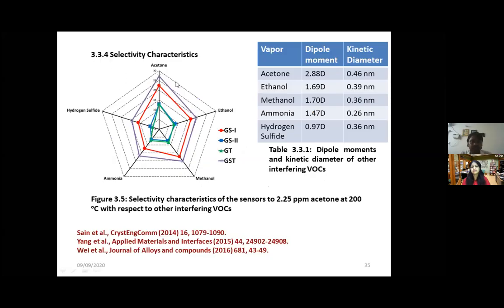And this is the selectivity characteristics of all four materials. For GST, acetone responds to 26, and for hydrogen sulfide the response is less than 15, and it correspondingly decreases for all four materials here. This depends on the dipole moment. Acetone has a high dipole moment, and the dominant peak which we have seen in XRD, 101 for SnO2 and 110 for TiO2, is also responsible.